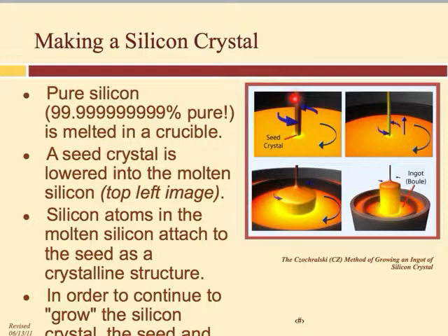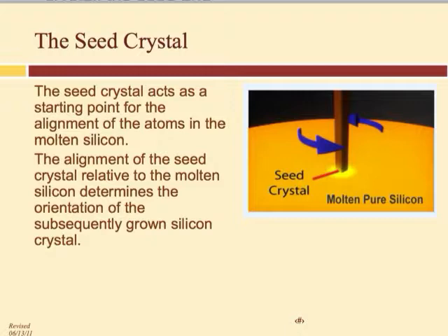And we'll show a video a little bit. Okay, so here's a close-up. Your seed crystal is right on the end. You just dip it right to the surface and slowly pull it out. The rod will rotate in one direction, and they actually rotate the bucket, they call it a crucible, in the opposite direction. And it's pretty slow. Okay? Very, very controlled. If you do it too fast, you'll get dislocations, and you won't have a constant crystal structure. It'll be a shift. Right? Like those polycrystalline.